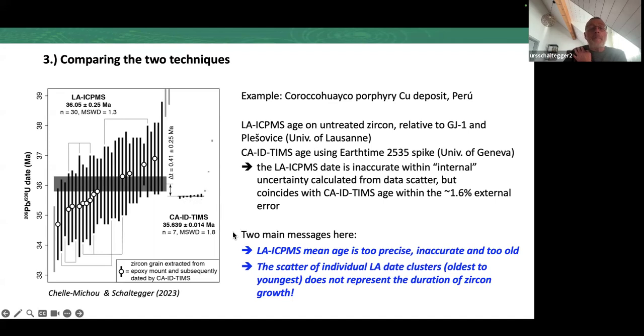So from this, it's too old, but when we now take into account the external reproducibility, again the 1.6% external error, then we get an overlap. So what we can take here as message is that the laser ablation date is too precise, is inaccurate, and too old. And what we should definitely never do is to take the oldest and the youngest of the laser ablation spot dates to calculate the duration of zircon growth. I have seen this in some papers. This is of course forbidden, because this is analytical scatter.